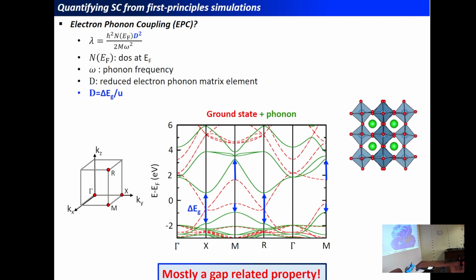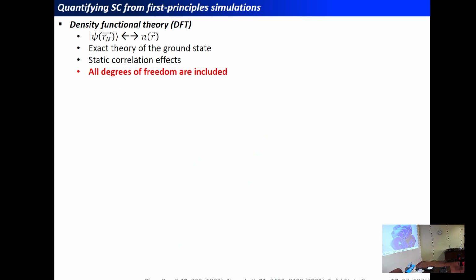So to do that, we have to use band structure simulations. And for that, one of the best techniques, I would say, is density functional theory, in which we substitute the knowledge of the many-body wave function, which depends on 3N degrees of freedom, with the sole knowledge of the electronic density that only depends on 3 degrees of freedom. And this theory is an exact theory of the ground state, in which we model static correlation effects, but also in which we can include all degrees of freedom, meaning also the structural degrees of freedom on top of the electronic ones. So nevertheless, it's not so wonderful in DFT.